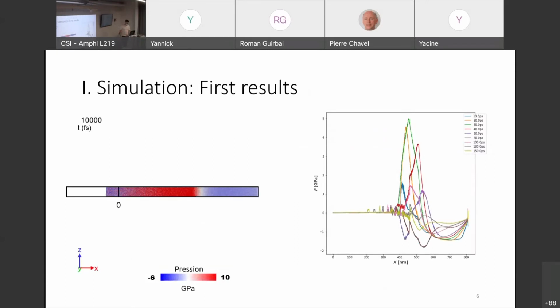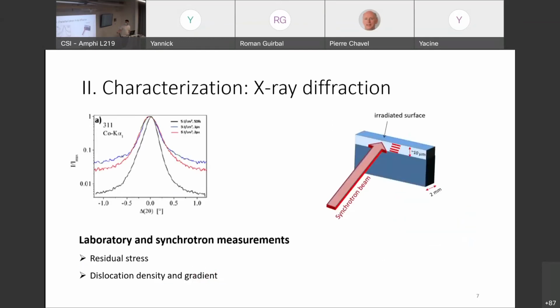So these are the first results we have. Here we can see the pressure as a function of the time after the pulse of the laser. We can see the propagation and the attenuation of the pressure through the depth of the material. And from those simulations, we hope to know the best parameters we will use then in experiments. The second part of the work will be to characterize, thanks to X-ray diffraction, the residual stress and the dislocation density in the material.